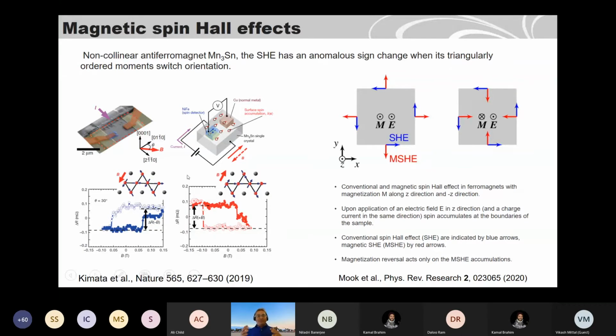That means in this material the magnetization is not collinear. So when you measure the anomalous Hall effect in such a material, you get a net magnetization. It's an antiferromagnet, but you can find the magnetization. So what people have done is they wanted to see if this material can give a spin Hall effect and if it is dependent on the magnetization of the material. Because this is also a theory paper that just came out last year. So they show what can happen with the spin Hall effect.